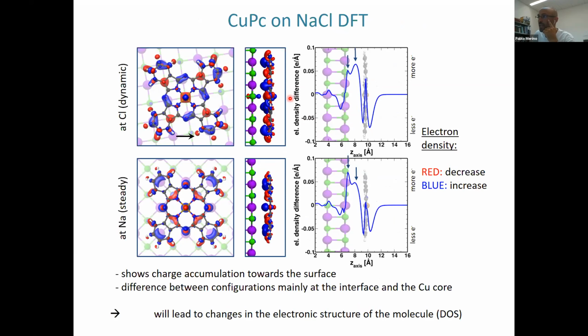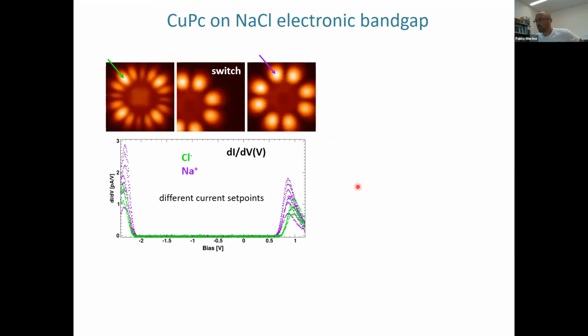What we see is there is a charge accumulation at the interface, and we see that between the molecule sitting on chlorine and the molecule sitting on sodium, the charge accumulation sits closer to the molecule or closer to the interface. And of course, these changes will have to lead to some changes in the electronic structure of the molecule, and we did dI/dV on the same molecule with the same tip after switching.